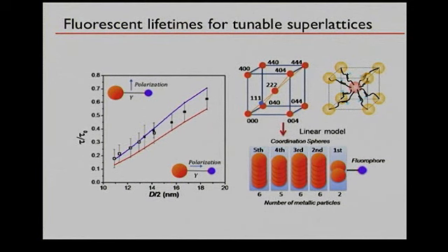So what we found out is that this change of the fluorescence lifetime of the chromophore is really sensitive, to a large degree, only to the first 2 coordination spheres. What is important is that the number of neighbors and their location pretty much determines the optical response. At the same time, it's clear from this type of experiment that maybe the precise 3-dimensional structure over long range order is not necessarily important here, but the short range neighbor positions are really important for the optical response of rhodamine.